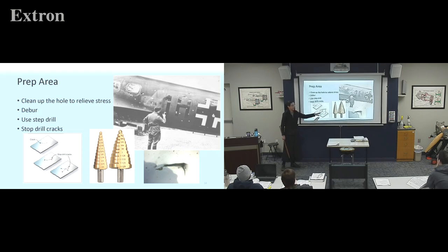So if you stop drill it, like, I'll come back, patch it up later, then eventually it will start cracking out again. And sometimes it'll allow like 2 to 3 times of stop drilling, or it'll give a length, or if it starts cracking out this way, let's say 4 cracks. But it'll be in the manual and it'll give you limitations on at what point you need to patch it.